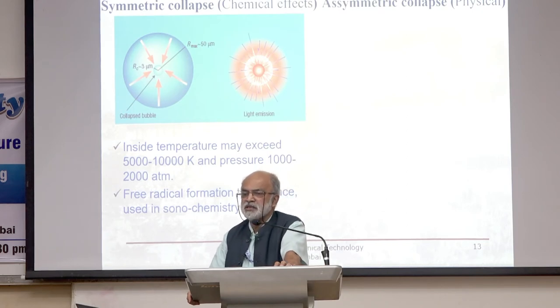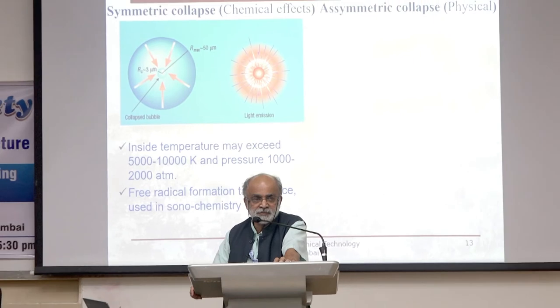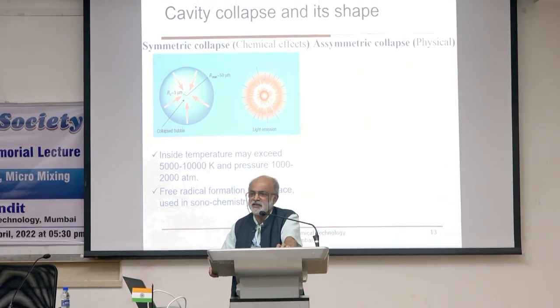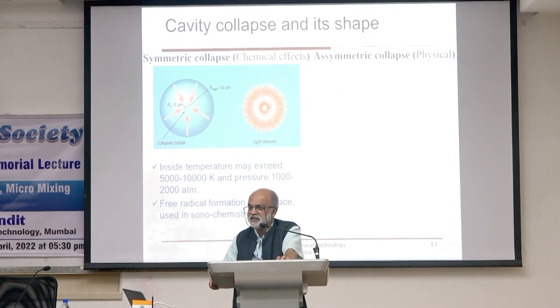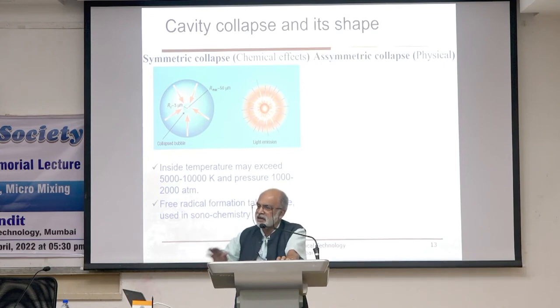It generates temperatures in the range of 5000 to 10,000 Kelvin. The surface temperature of the sun is approximately 5800 Kelvin. So you can imagine the kind of conditions which are generated inside this collapsing cavity. N number of reactions, ionic reactions, can take place, and if you are in a position to capture that... many times if you have water vapor inside this particular cavity, water vapor dissociates beyond 3000 degrees centigrade into H and OH. OH being an extremely strong oxidizing radical can oxidize the pollutants, and H of course can reduce. So reduction oxidation reactions, redox reactions, can also be carried out very easily.